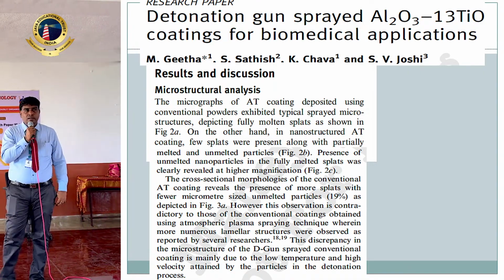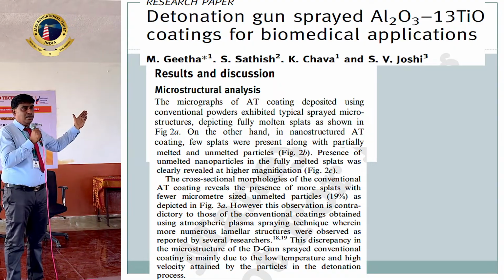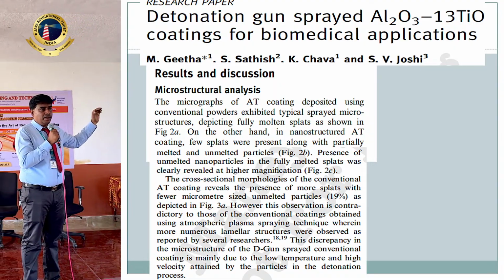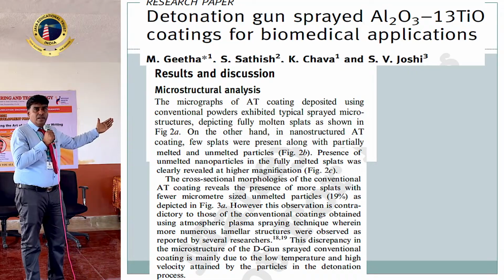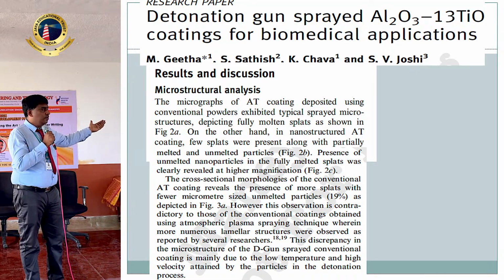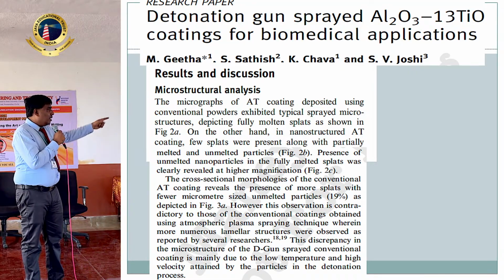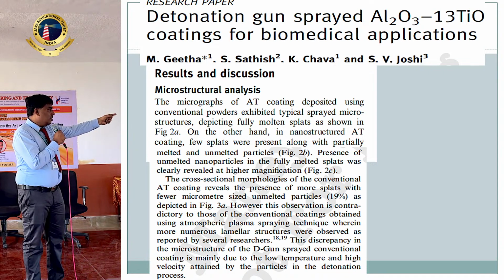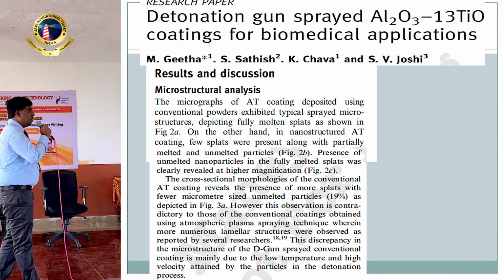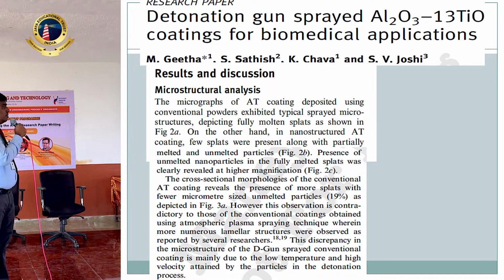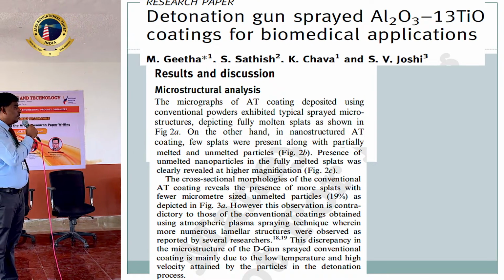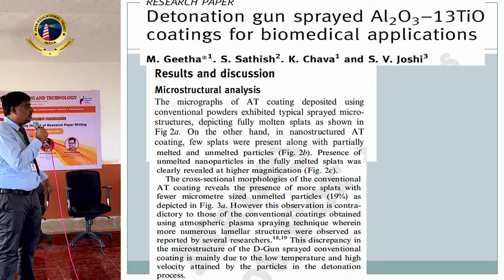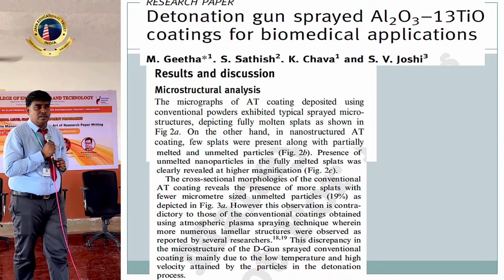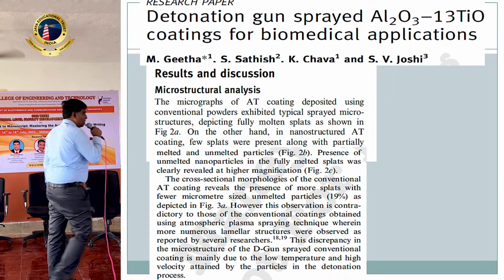So my result is in contradiction with the results reported by some others who performed the same work using some other technique. And I have explained that this variation or discrepancy in the microstructure of the sprayed conventional coating is mainly attributed to the lower temperature and high velocity attained by the particles in the detonation gun process. So this is very important.